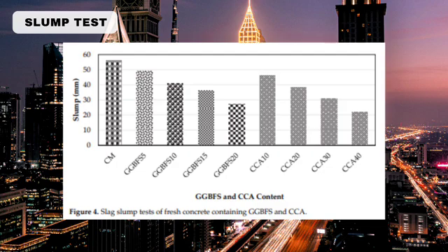as an FA replacement. The slump levels are 12.50%, 26.78%, 35.71%, and 51.78%, with GGBFS levels of 5%, 10%, 15%, and 20% respectively. The slump levels are 17.86%, 32.14%, 44.64%, and 51.46%, with CCA levels of 10%, 20%, 30%, and also 40%. Both sets of slump levels are lower compared to concrete made of PC only.